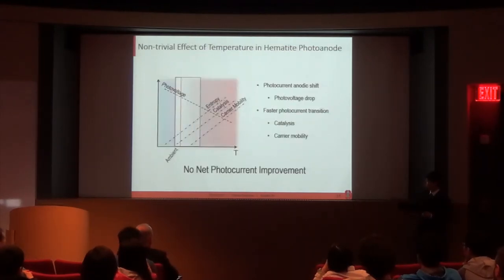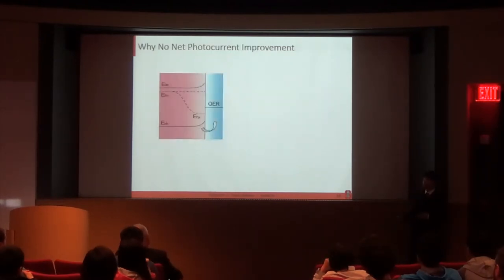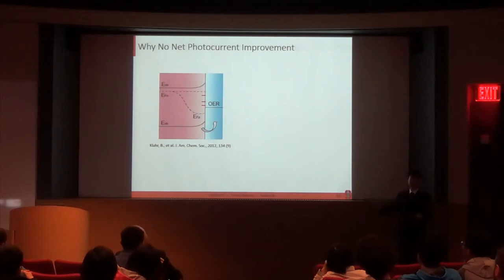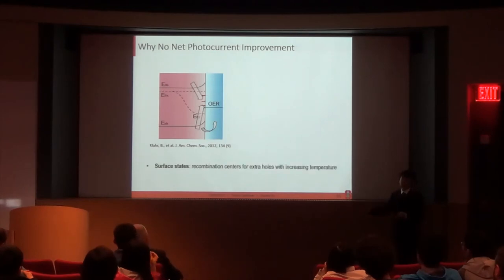So it looks like increasing temperature is not worthwhile, but we want to know why. So I looked closer at this band diagram, and I realized that there are a lot of surface states at this hematite-liquid interface, which is well established from the literature. These surface states serve as recombination centers for electrons and holes. So even though at high temperatures there may be extra holes that can reach this interface, they will just recombine at these surface states rather than participate in the oxygen evolution reaction. Therefore, you don't see increased photocurrent.